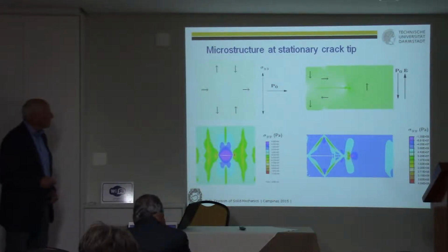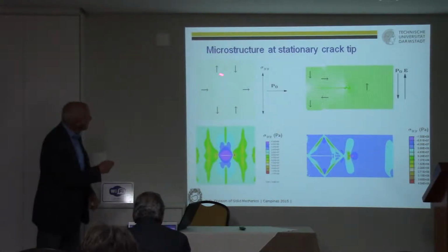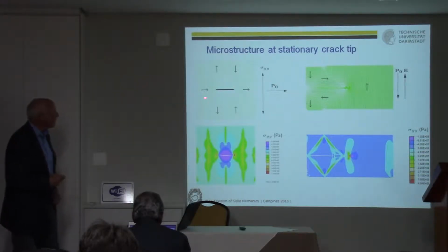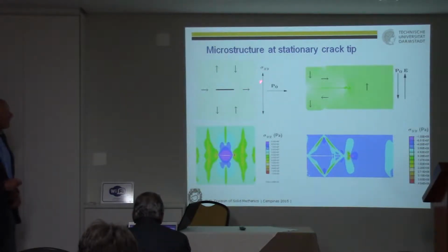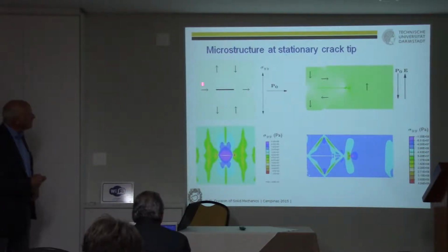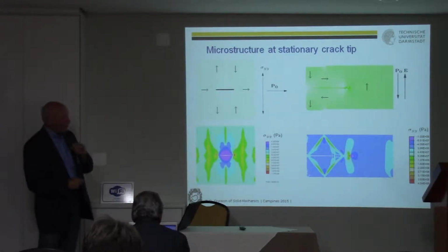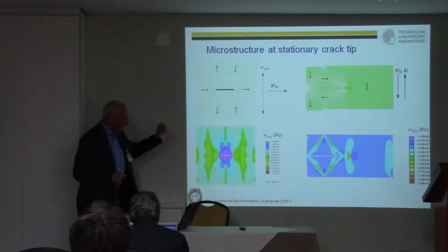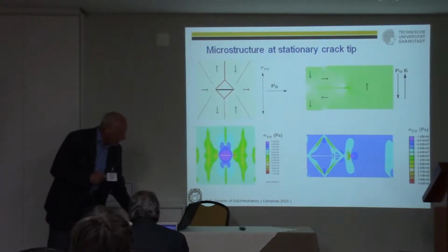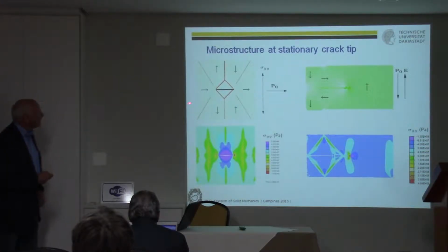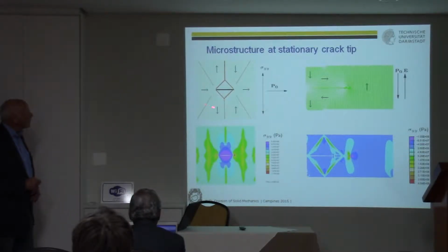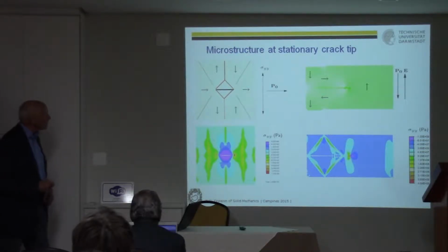Now let's consider some cracks. Here in this figure I can show where the crack is. It's loaded by a mechanical load, and the initial polarization was in this direction, and after loading you see, or perhaps you cannot see, these little green arrows. To make it a little bit easier for you, I have indicated here the domain walls, which separate the different domains with the different polarization.